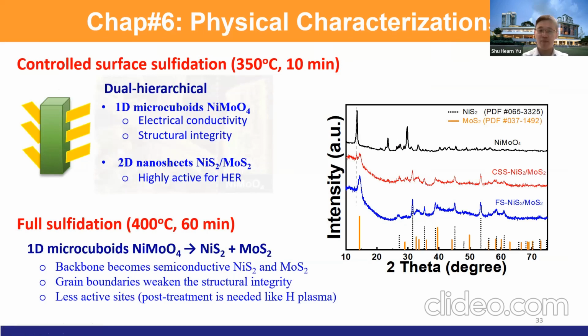This is one of the reasons why it can be performed at high current density, because the catalyst we have right now is not made by using a spray gun. If you spray your material on carbon fiber paper at high current density, the sample will detach. In this case, these materials are grown directly on the nickel foam. You are not trying to spray or deposit the material on top. You grow it; the material grows from itself. So it has a very intimate connection and will not detach easily. That's the reason why it can perform at high current density.